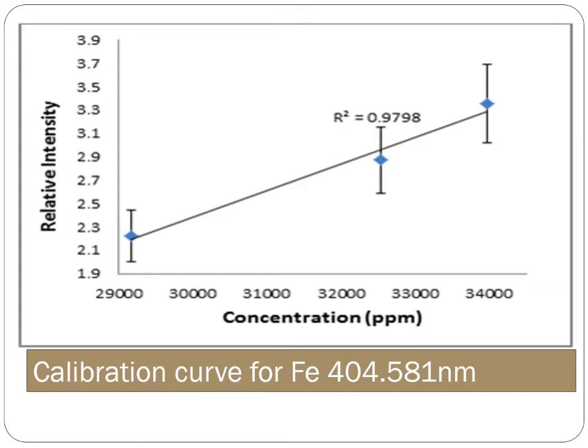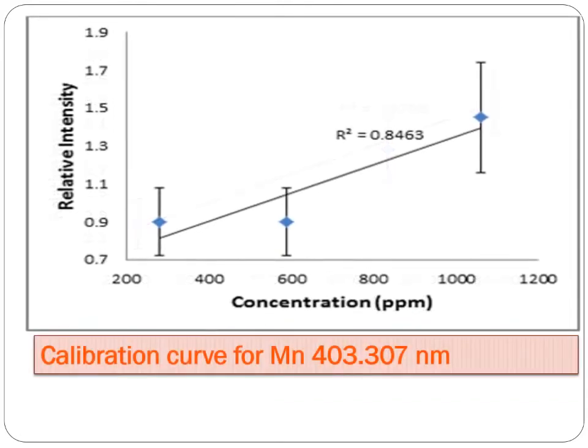If we have different concentrations of the same element, we can make a calibration curve. This is a calibration curve for iron at the 404.5 nanometer line at different concentrations and different intensities for the same line. This is a calibration curve for manganese, with different concentrations of manganese from 200 to 1200 ppm.